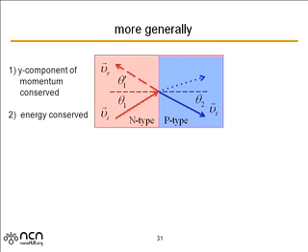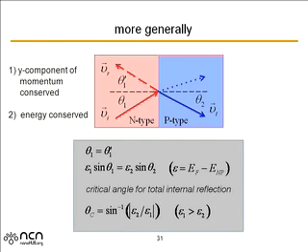If you want to make sure you understand all of this, you could relax the assumption that this is a symmetrical junction with the same energy on each side, same kF on each side, and you could do it more generally. And the relation you would get is that angle of incidence is always equal to angle of reflection, but we would get epsilon 1, this energy difference between the Fermi level and the neutral point on the n side, sine theta 1 is equal to epsilon 2 on the p side, sine theta 2. So this energy difference is playing the role of the index of refraction. And since it's positive on the n side and negative on the p side, we get a negative index on the p side.